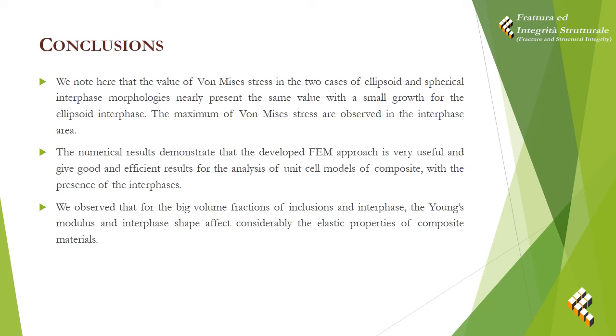With the variation of volume of interfaces from 1, 1.5, and 1.3 times the inclusion volume, we note the increase of elastic properties in all cases for both spherical and ellipsoidal interfaces. We note that the stress distribution in the two cases of ellipsoidal and spherical interface morphology may represent similar values with a small increase for the ellipsoidal interface. The maximum stress values are observed in the interface area.